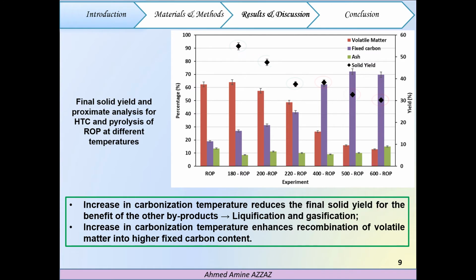These findings were further confirmed when performing the proximate analysis. Raw olive pomace initially presented a high value of volatile matter and low content of fixed carbon. When increasing the hydrothermal carbonization temperature, a decrease in the volatile matter was noted due to the condensation of carbon content, which explains the increase in fixed carbon percentages. This tendency was further amplified when changing the carbonization process here.